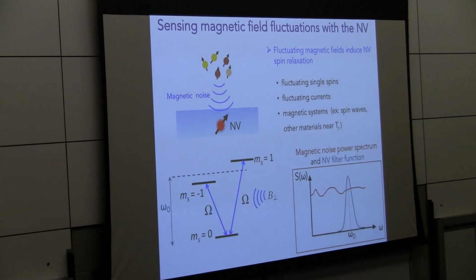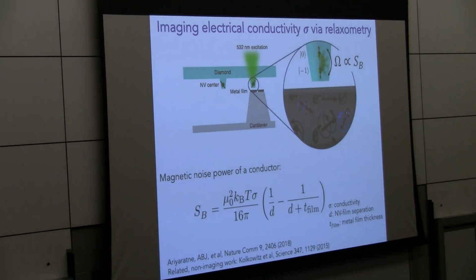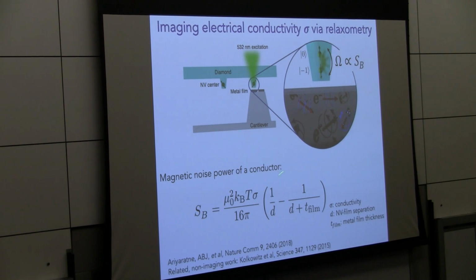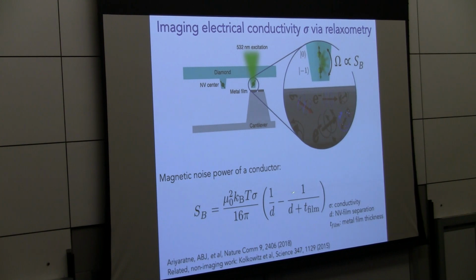So to demonstrate this, we did this type of relaxation T1 imaging to probe the fluctuating magnetic field produced by fluctuating currents, to in fact image the conductivity of a material. As I mentioned, this relaxation rate omega is proportional to the noise power spectrum at that splitting between the 0 and the -1, which in our case is on the order of gigahertz. If I have a conductor, then electrons are moving around randomly back and forth, exhibiting Brownian motion, and I can calculate quantitatively what the noise power spectrum of the magnetic field fluctuations is as a function of temperature, conductivity, separation of my NV center from this conducting film, and also the thickness of the film. Okay, so this is what we expect the magnetic noise power to be.